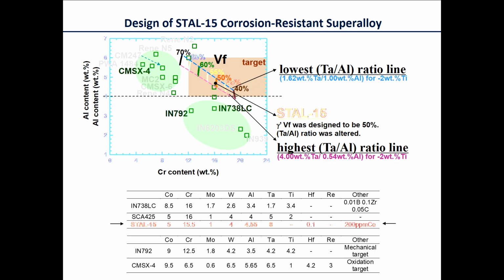And the concept here involved trying to balance the strength of the alloy, which is really strongly dependent on the aluminium content, for reasons I'll explain in a few moments, against the corrosion resistance, which depends upon the chromium content. And in this field, you can see that the aerospace type alloys tend to be in this bubble over here, and the land-based turbine people were working primarily over here at much higher chromium contents to get their corrosion resistance, but at much lower strengths. So we decided to invent new kinds of alloys in this region up here, with the idea of having the strength of the aerospace alloys, but with much higher chromium content to give you good corrosion resistance.